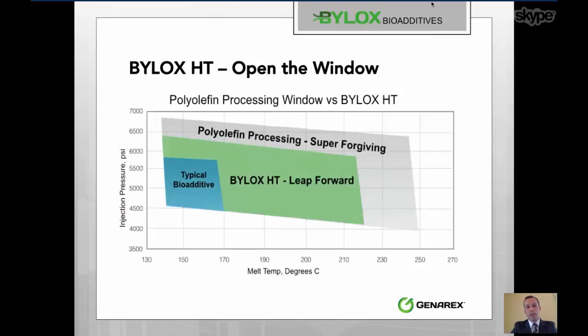So one of the big things that we've seen, this is kind of what we talk about when we look at what Bylox HT brings to the table. When you look to incorporate a bio-based additive or filler into a polyolefin, you're used to polyolefins having this very wide processing window where they can go with a low shear or high shear process, they can go with a low temperature or a high temperature material. And the little blue rectangle here that you see is where most bioadditives tend to fall. It's very difficult for them to participate with polyethylene or polypropylene because they simply break down too early. With Bylox HT, we've completely blown the roof off of that assumption.